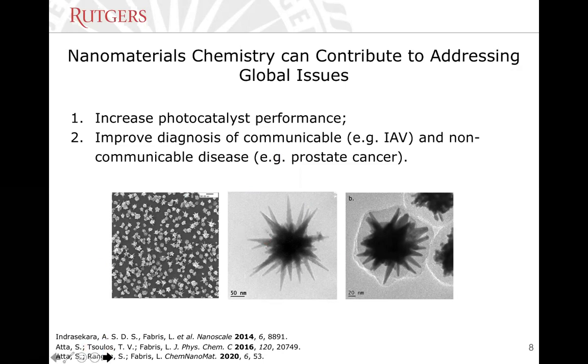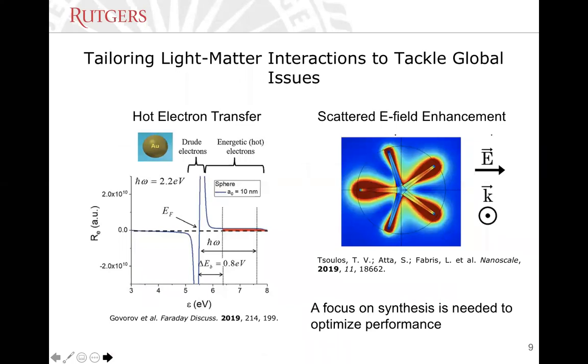So if we think about plasmonic nanoparticles with respect to the problems we're trying to address, we can see two different areas of interest. On one hand, if we look at hot electrons and hot electron photocatalysis, we realize that upon absorption of radiation by plasmonic nanoparticles, there is the generation of a relatively high number of hot electrons that have large energies. So these highly energetic electrons, if they can be extracted from the nanoparticles, can do things. For instance, reduce molecules and do reduction chemistry in the surrounding environment.